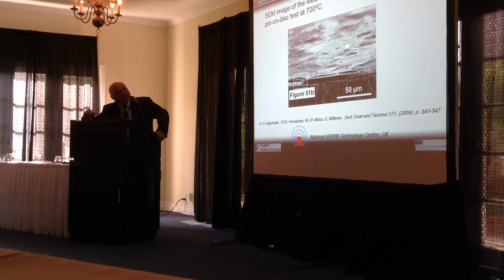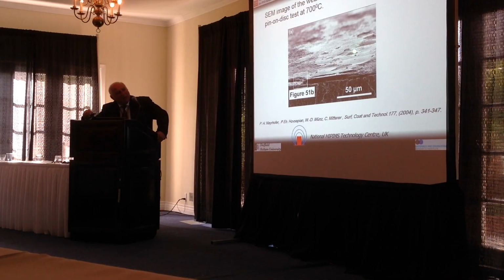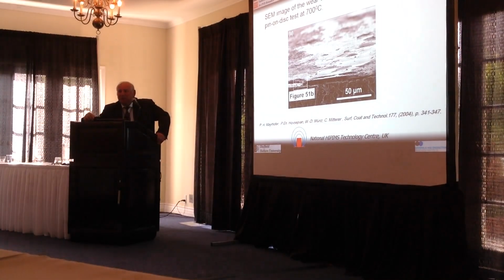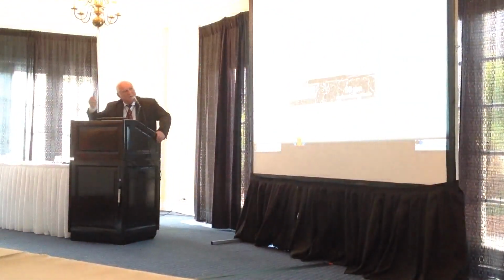And in collaboration with Oerlikon, I think Paul, I don't see him in the audience, is here, he produced this nice SEM picture of the wear track from a high temperature pin-on-disk test, 700 degrees C. You can see this structure which shows you that the ball is actually sliding against molten material, because 700 is above the melting point of vanadium pentoxide. So this was a very interesting result.